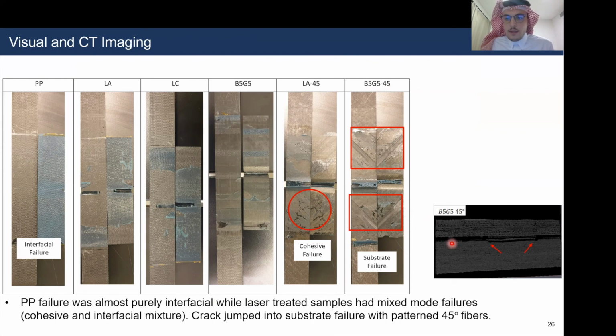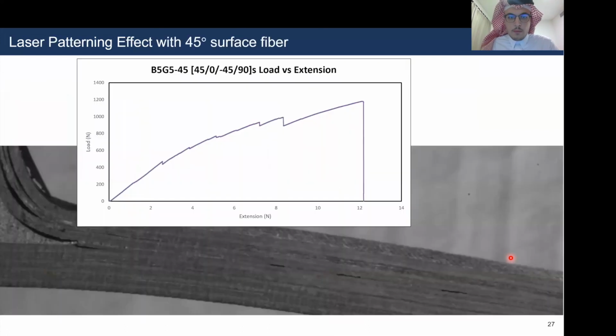So this was verified using CT imaging, and I noticed that the crack propagated at the interface and then entered the skin, propagated inside the skin, and then went back into the interface. This resulted in an increase in the energy dissipation as a non-local damage mechanism happened in the 45 degrees. However, this was not as high as the improvement produced with the BSG5 adhesive ligaments illustrated earlier.